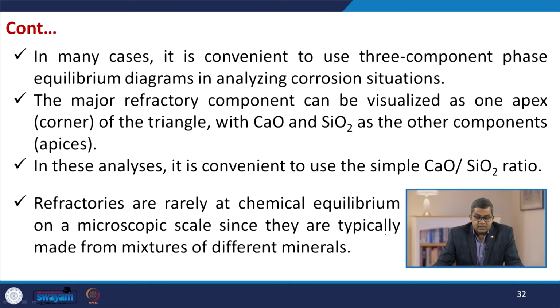In many cases, it is convenient to use the 3-component phase equilibrium diagram in analysis of corrosion situations. The major refractory component can be visualized as one apex of the triangle with CaO and SiO2 as the other components. Now, in this analysis, it is convenient to use the simple CaO over SiO2 ratio. The refractories are rarely in chemical equilibrium on a microscopic scale since they are typically made from a mixture of different minerals.